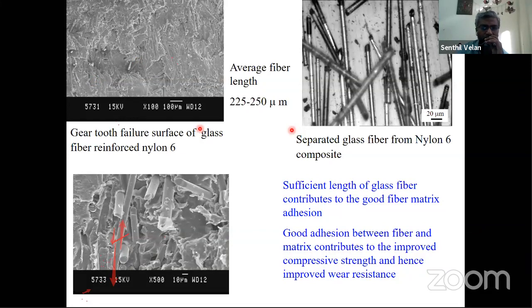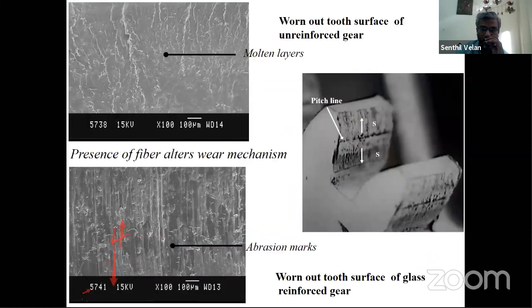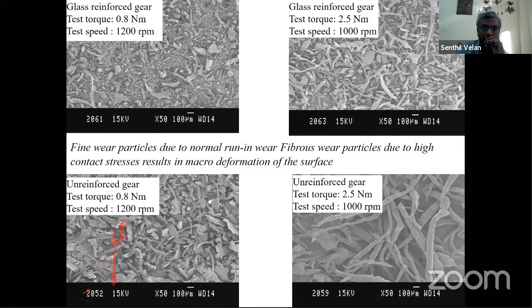But on a typical worn out surface also, you will see how the wear marks are observed from the pitch surface and so on. What is surprising, if you look into this, to compare the wear particles between the glass reinforced and unreinforced material, you can see a big difference between the glass reinforced and these two, which are the unreinforced material.